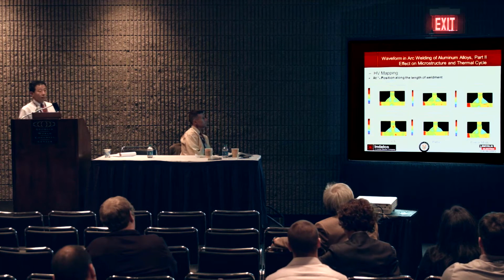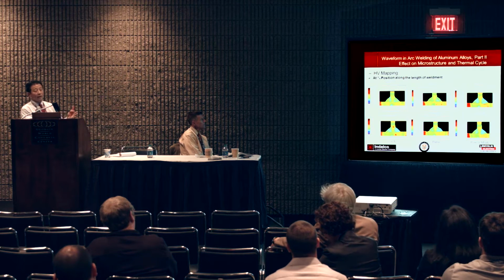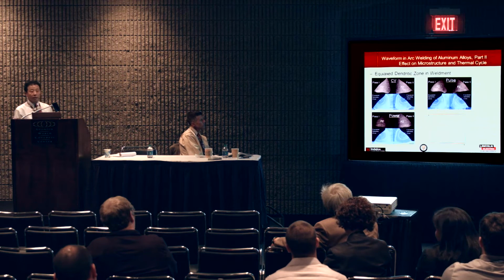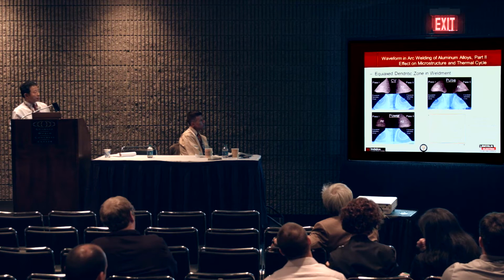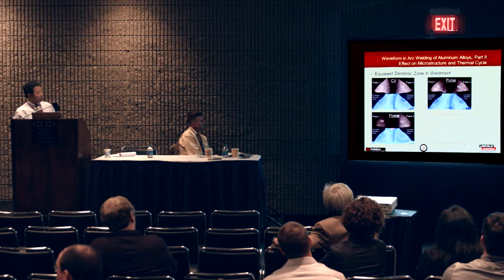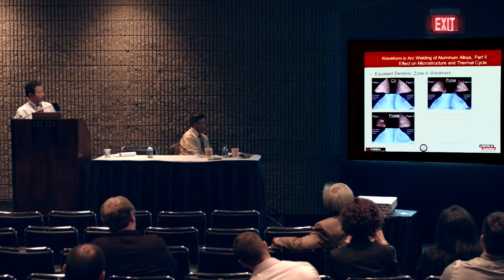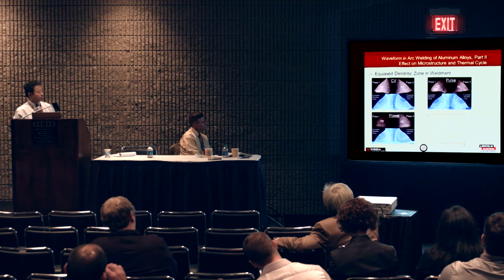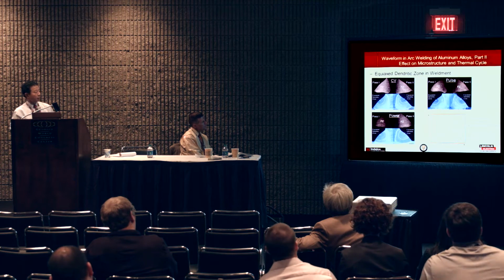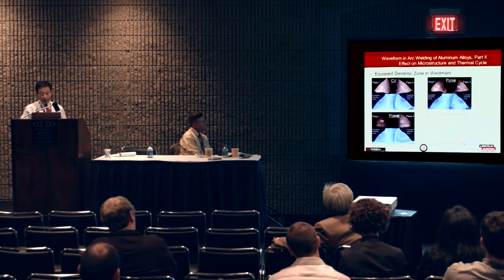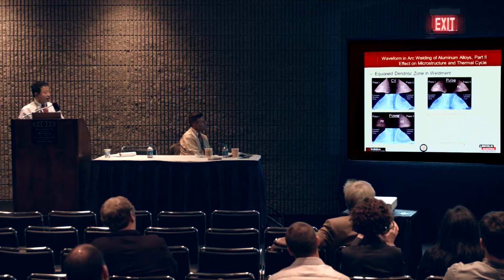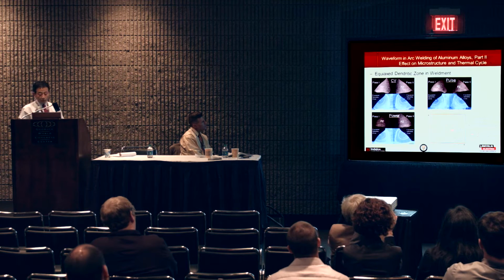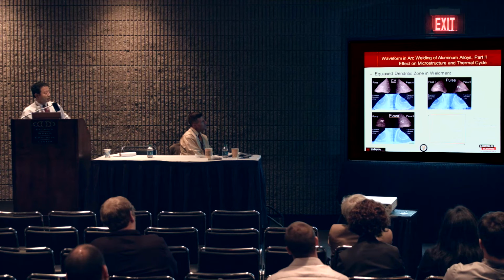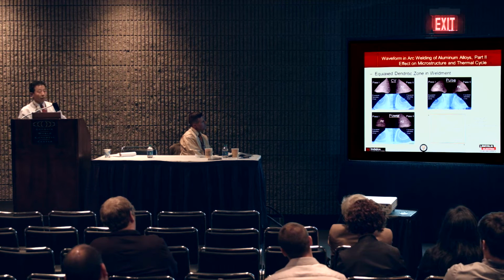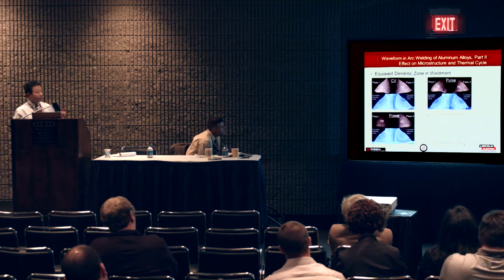And based on those, which I presented last year, I then needed to understand why. So this year we did lots of microstructure analysis. You can see that, from different modes, this is CV, this is pulse, this is the power mode, definitely the power mode gives you the biggest equiaxed microstructure. Also, your temperature gradient changed from the power mode to the pulse mode to the CV, and your cooling rate is highest for CV, then pulse, then power mode, which results in a change in the size of your equiaxed zone, which gives you the highest strength.